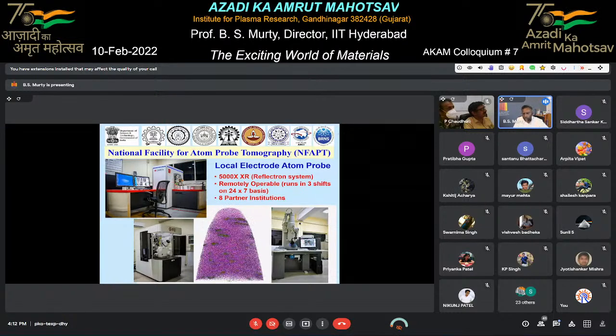This is called an atom probe, and this is one such image, where each pink dot that you see is an atom of iron. So this is a steel sample with some nanoparticles of yttria inside. All these green particles that you see are yttria nanoparticles, Y2O3, and they are all 2 nanometers in size or so. And we can actually find out the stoichiometry of the particle.